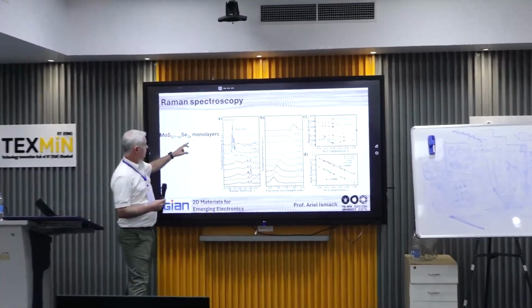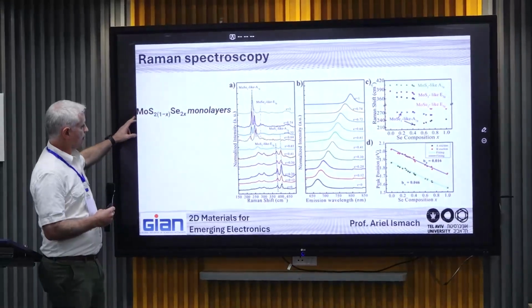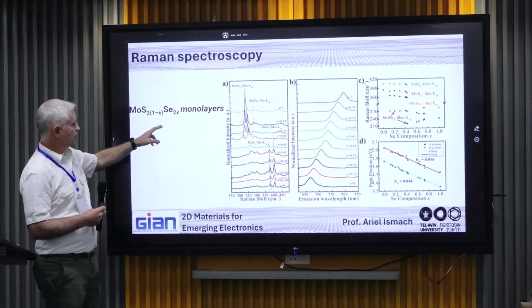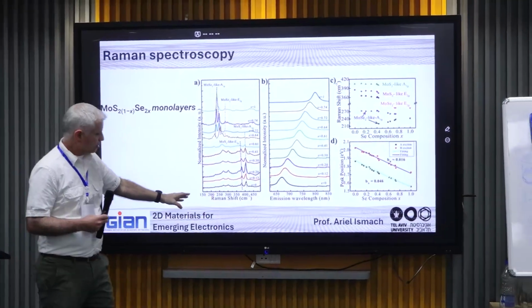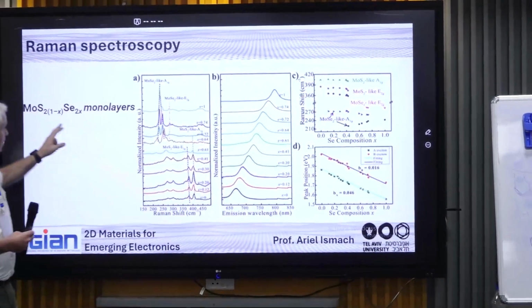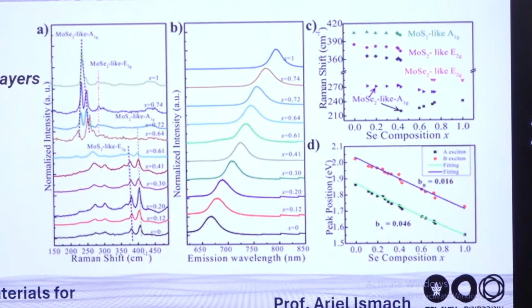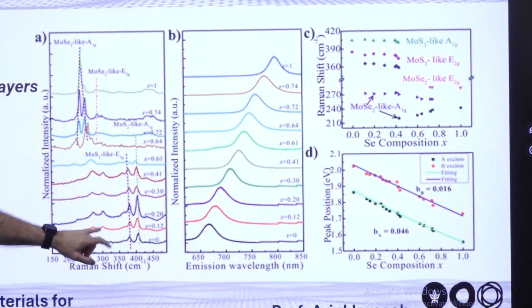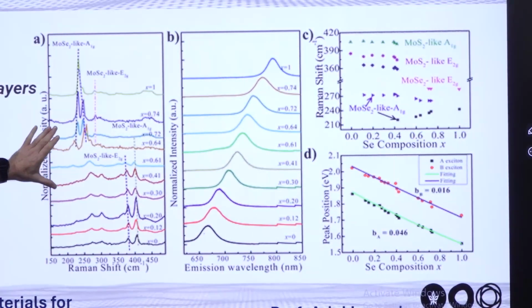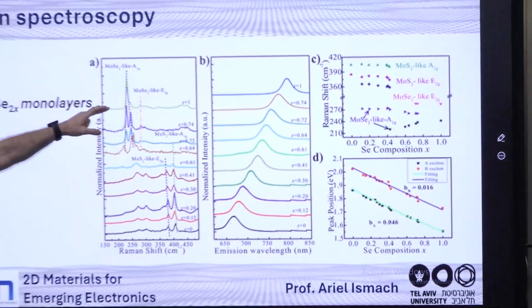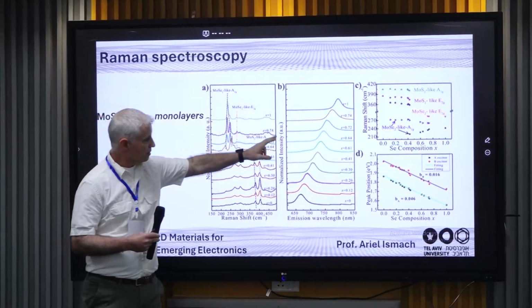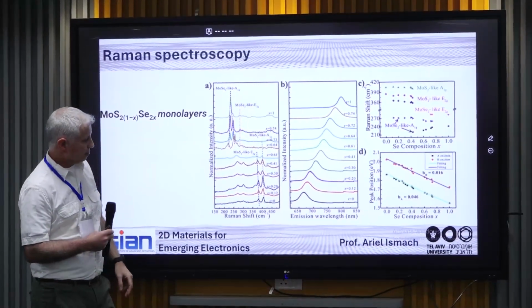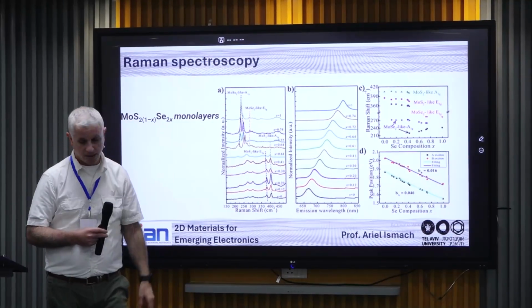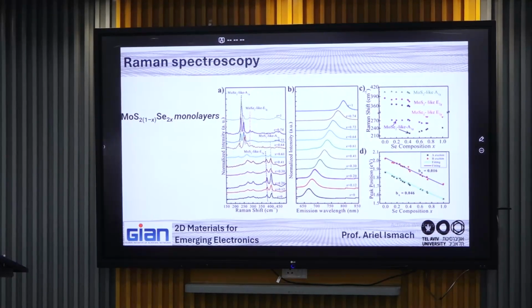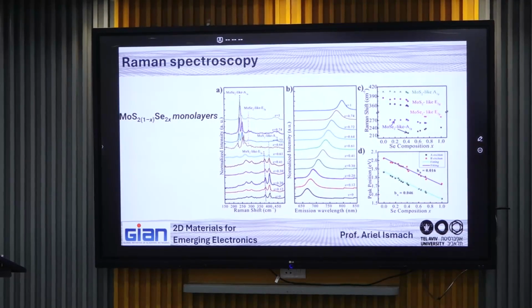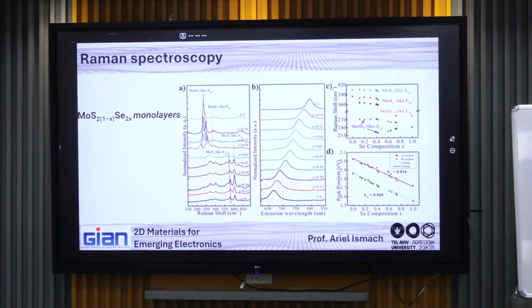Here you can see the Raman in this work where they make alloys of sulfur and selenium monolayers. You can see the Raman spectra from when X is 0, so you have only the sulfide, and how it switches. Here you have the alloy and then you have only the molybdenum selenide. And the same you can see in the PL spectrum, right? It changes according to the composition, as I showed you before, the relative composition of selenium.